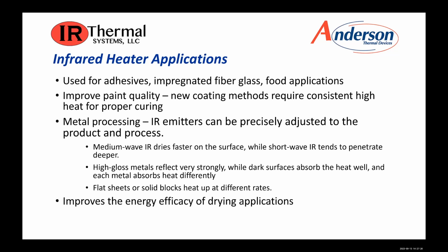So infrared heating applications are used for adhesives, impregnated fiberglass, food applications, to improve paint quality. New coating methods require constant high heat for proper curing. Metal processing, IR emitters can be precisely adjusted to the product and process. So medium wave IR dries faster on the surface, while short wave IR tends to penetrate deeper. High gloss metals reflect very strongly, while dark surfaces absorb the heat well, and each metal absorbs heat differently. And flat sheets or solid blocks heat up at different rates. So in general, IR improves the energy efficacy of drying applications.